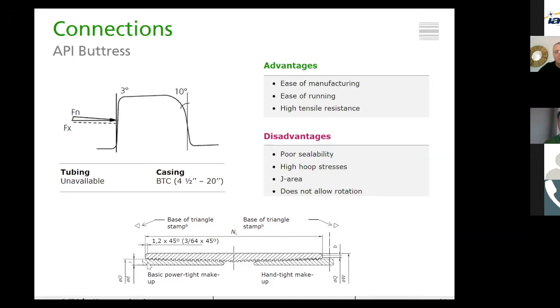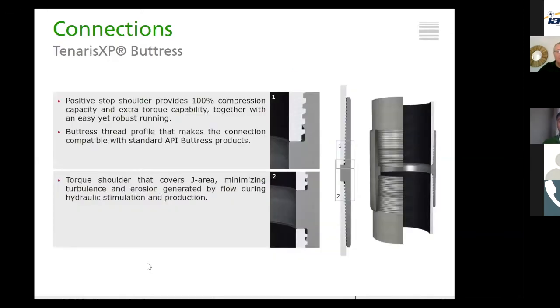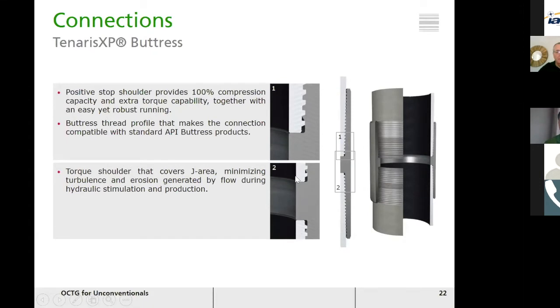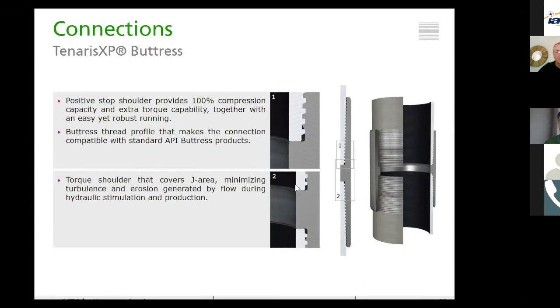This profile is actually used for many proprietary connections, such as the TenarisXP buttress. This is a buttress modified, fully buttress compatible connection that provides 100% compression capacity and extra torque capability through a positive stop shoulder shown here in the second cutaway view. The shoulder also covers the J area of the connection, minimizing turbulence and erosion generated by flow during hydraulic stimulation, and production in case some fine sands are produced.